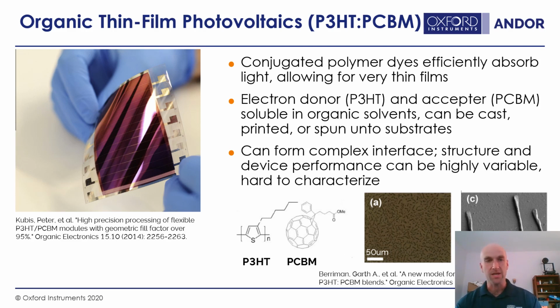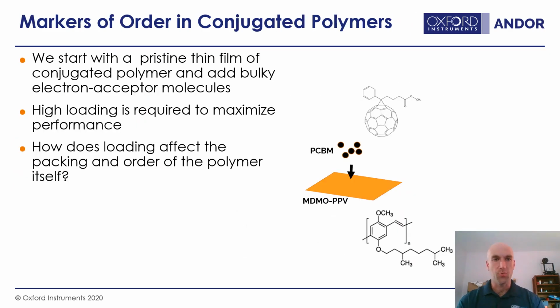One question worth addressing. We start with a pristine thin film of conjugated polymer, which might be fairly well ordered or at least have well ordered domains, and we add in a bulky electron acceptor molecule at a fairly high loading. We're not doing that after the fact, we're doing this together, but imagine you have this nice pristine sheet where things are allowed to either crystallize or at least to order fairly well, and now we're stuffing in molecules, large bulky molecules, sterically very bulky molecules.